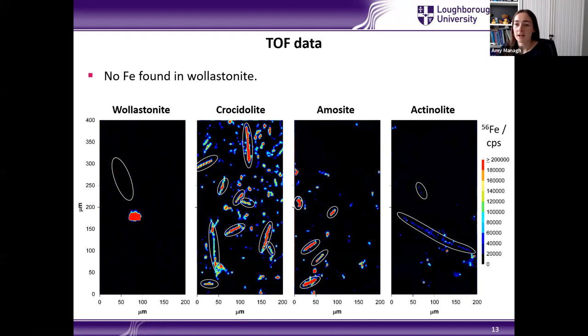If we look at the iron data now, we see signals for crocidolite, amosite, and actinolite. There's no iron that was found in our wollastonite sample. There is a little dot here that you can see in that sample. This was actually not a fiber, but a piece of cellular debris that was present on the slide there. So within the fiber region, we didn't see any iron signals there.